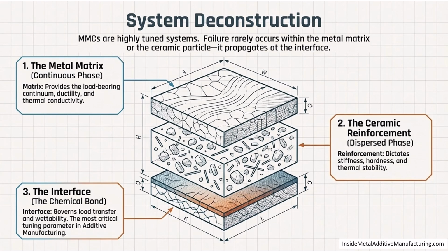First, the metal matrix, our continuous phase that provides the load-bearing continuum. Second, the ceramic reinforcement, the dispersed phase that dictates stiffness and hardness. But arguably the most critical and the most difficult to tune in additive manufacturing is the interface. Failure in an MMC rarely begins in the matrix or the particle. It propagates at this chemical bond.